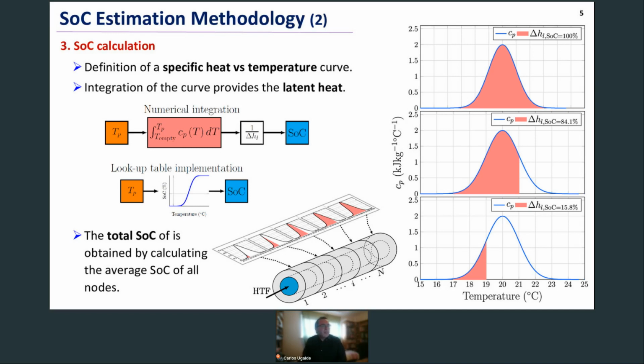The final step in the state of charge estimation methodology is effectively the calculation, which requires first to obtain a specific heat against temperature curve of the PCM. However, this may be directly provided by a manufacturer. If this curve is integrated in time against a defined range of temperatures, the latent heat value is obtained. This is nothing else than obtaining the area below a curve.